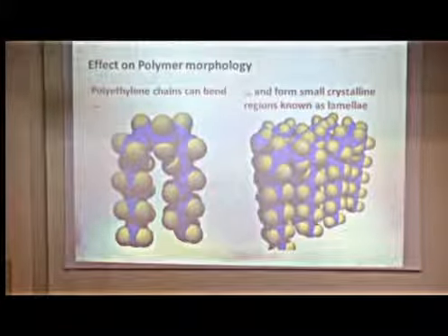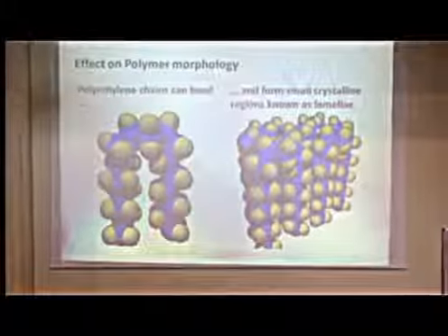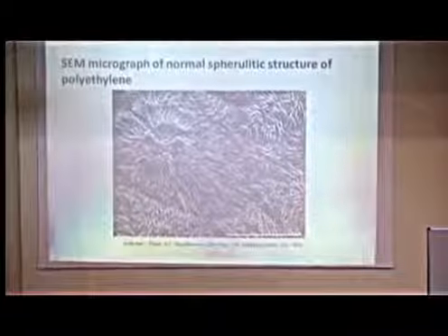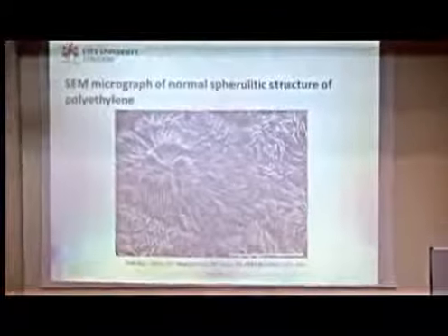I don't know whether Michelle would agree with that, but it's actually got these in, which are, in a sense, nanoparticles. They're the crystalline nanoparticles of polyethylene in a host matrix of amorphous material. So in a funny sort of way, polyethylene is almost intrinsically a nanodielectric in itself.